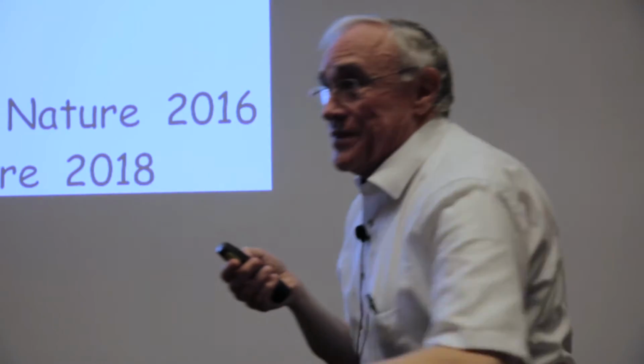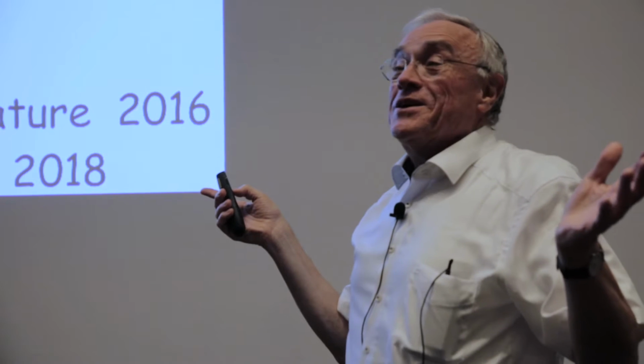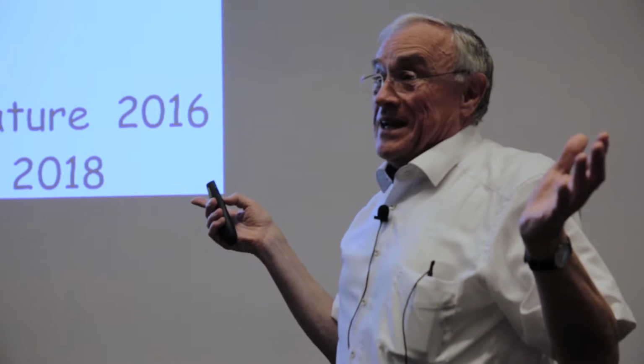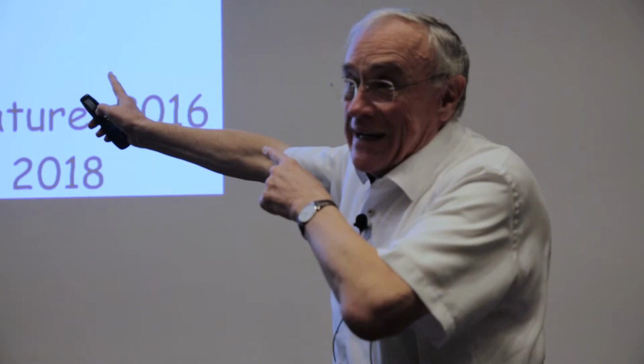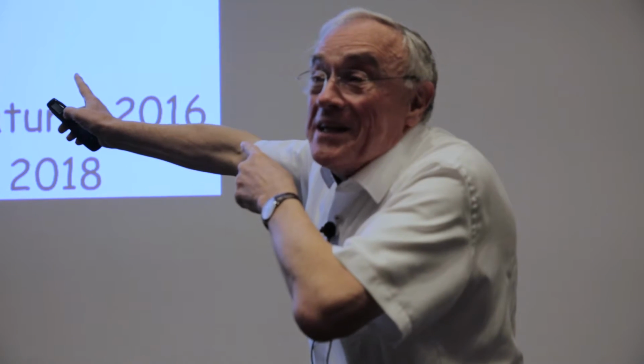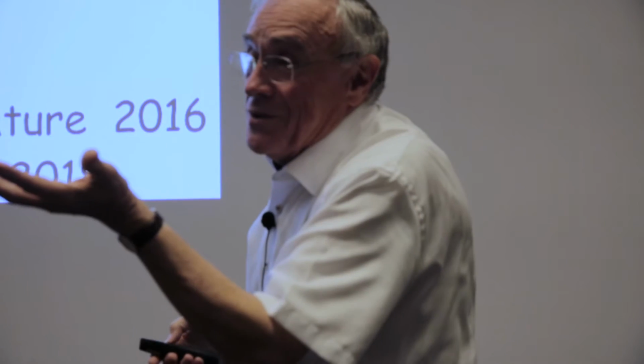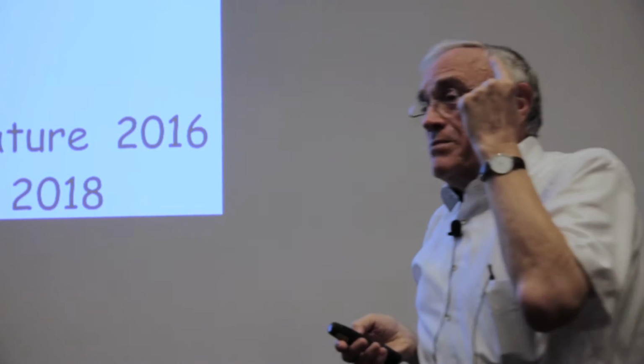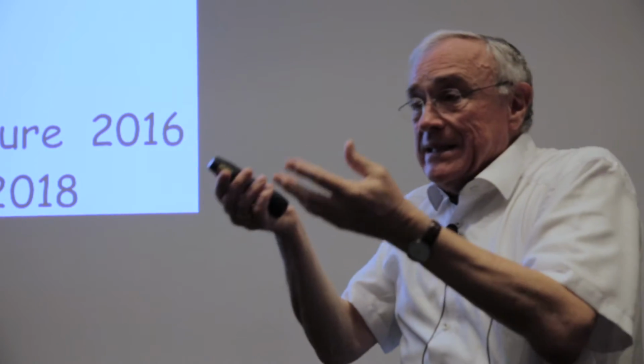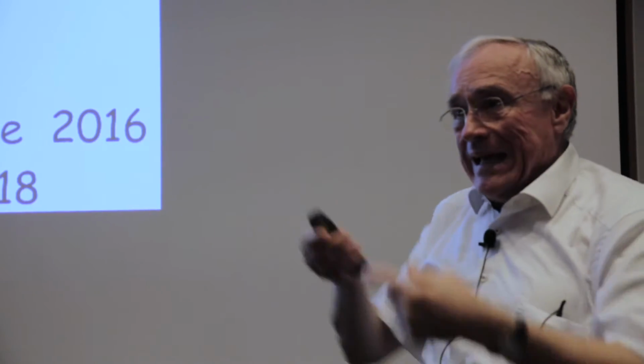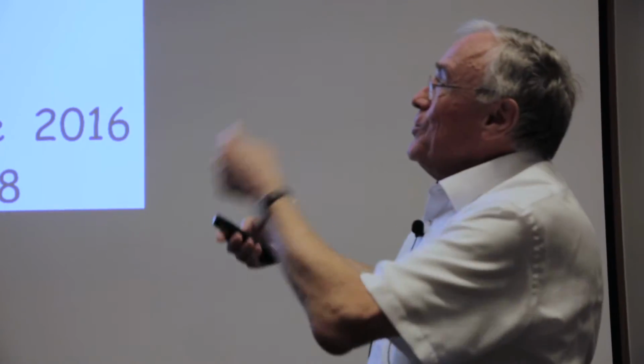We need, at the end, to have them on a surface. Why don't we make them on the surface? And the beauty is that we can monitor that by scanning tunneling microscopy in situ. If you remember what Gerhard Ertl did with carbon monoxide on nickel, in a sense, now you use small organic molecules, you put them on the surface, you activate them, and you control their